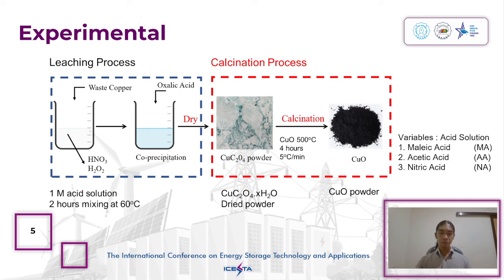Dark powder samples were collected and labeled as copper oxide. The copper oxide graphite composite was formulated by mixing copper oxide to graphite at a mass ratio of 3 to 7 via 2 hours of ball milling process.